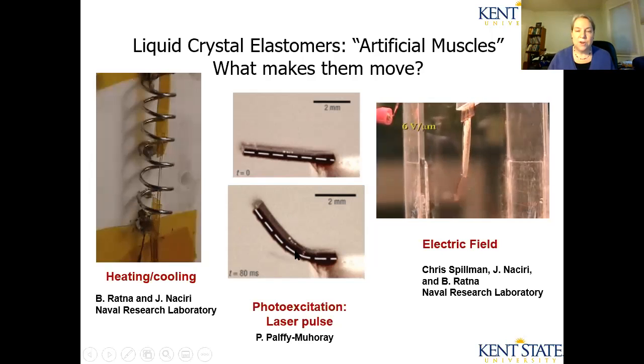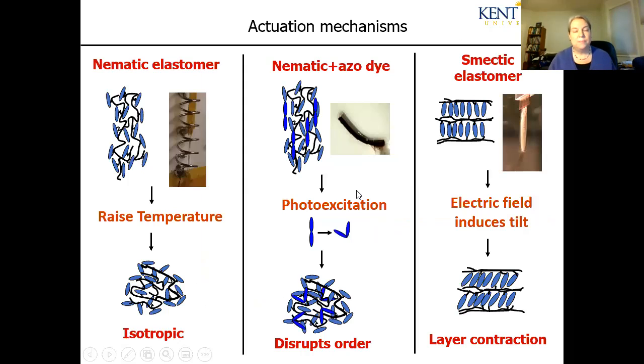And then here's one that's photoexcitation. I'm sorry, this one isn't a movie, it's just a still image. So you have a picture here of a cantilever beam, a couple millimeters long. This is work by Peter Palffy-Muhoray, my colleague at Kent State. And then you shine a laser pulse on it, it will actually bend in response to light. So we can have actuation by temperature, actuation by light, or actuation by field. I should also mention my colleague, Antal Jákli, is actually working on ionic liquid crystal elastomers that also flex in response to field. So this is a fast moving research area.